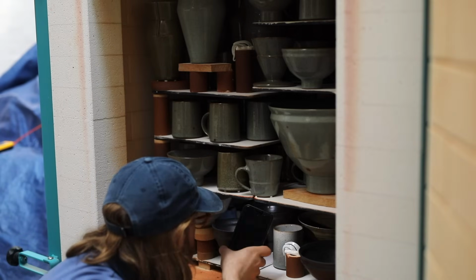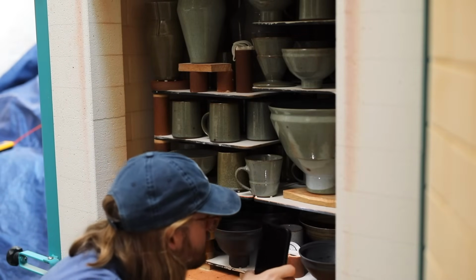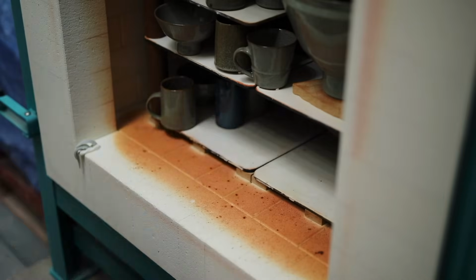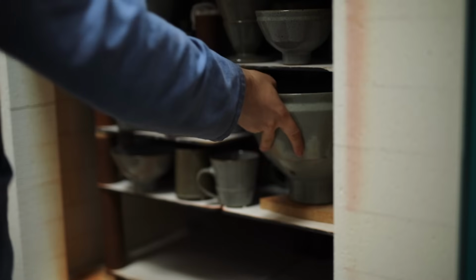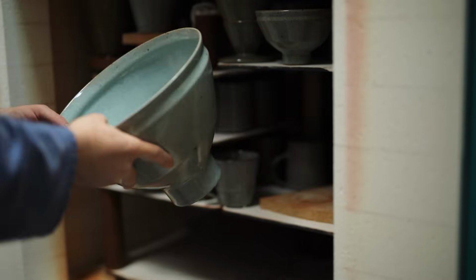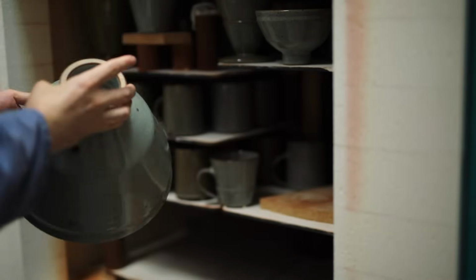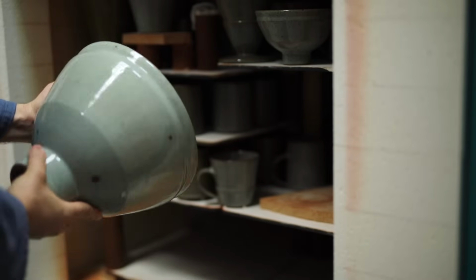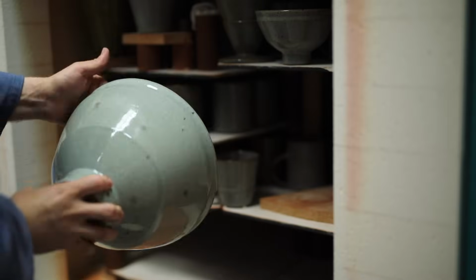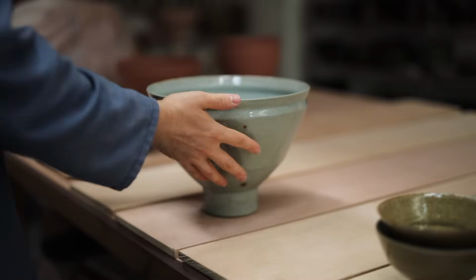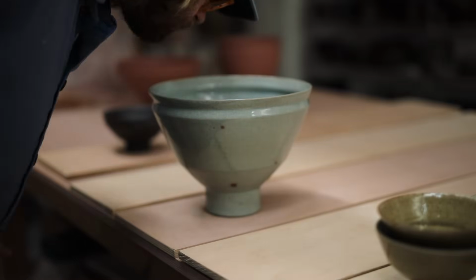The glaze looks even, and it's pooled in all the right places, and it doesn't look like it's stuck onto the kiln shelf. There are a few surprises here, mainly from metal inclusions that were mixed into the clay the bowl was made from. This has resulted in some red dots and some grey specks, too, from bronze and silver, respectively. There is some slight movement in the rim, but not enough for it to be detrimental.